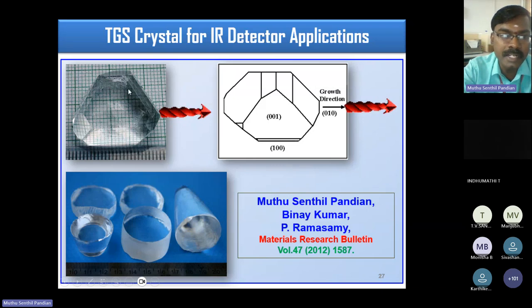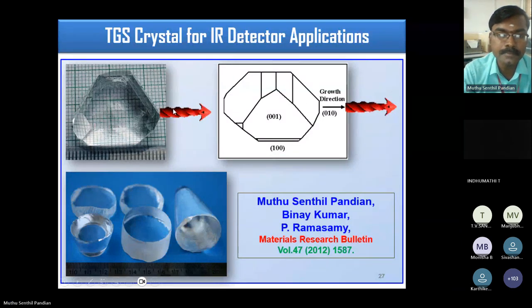As I mentioned, we cannot use the entire portion of the conventional method grown crystal. Only the small portion along the polar b direction will be useful for the IR detector application. So here what we have done is, we cut the crystal along its polar b direction and mount it at the bottom of the glass sample, and we grow this much larger size ferroelectric crystal for IR detector application. The remaining 99% will be wasted after cutting this small portion along the polar b direction.